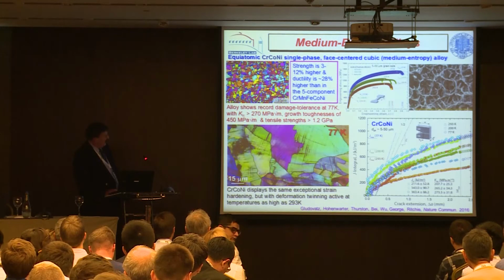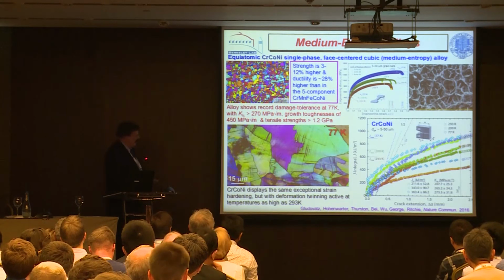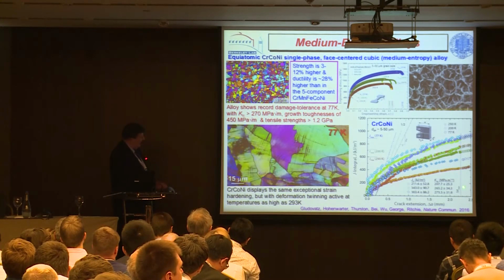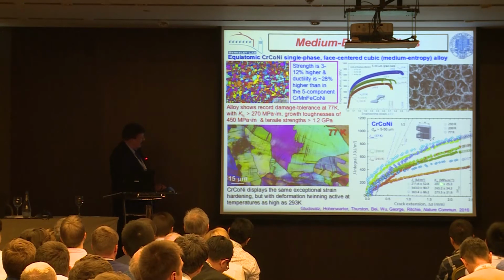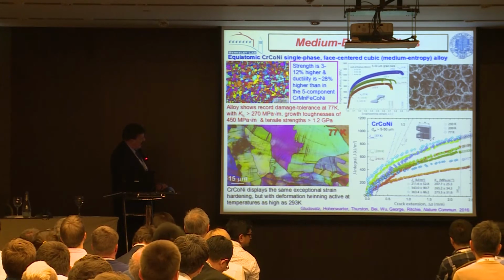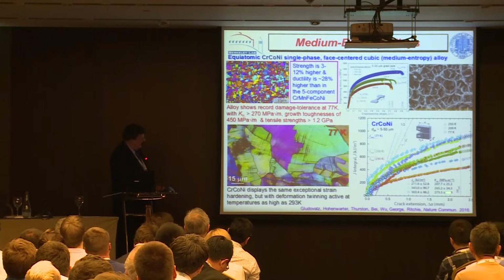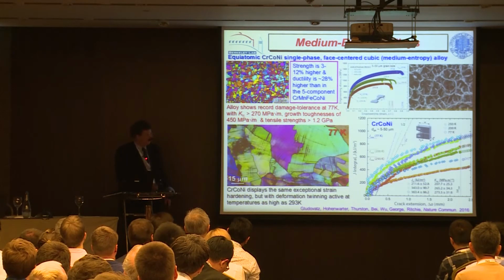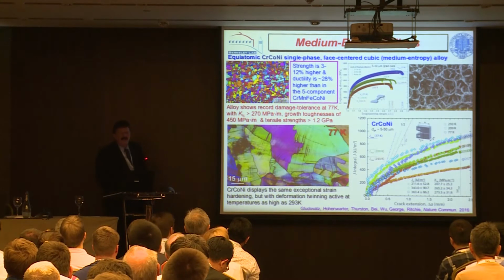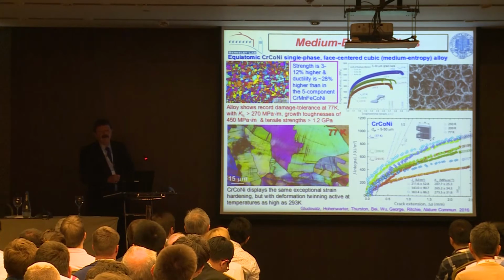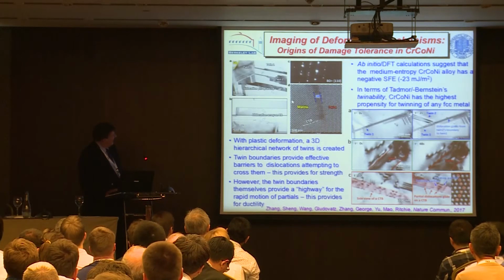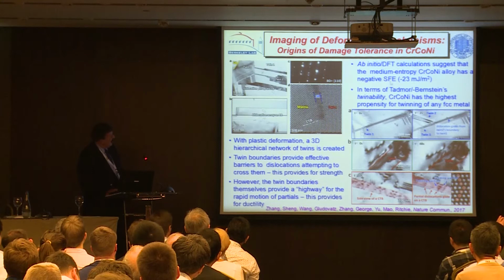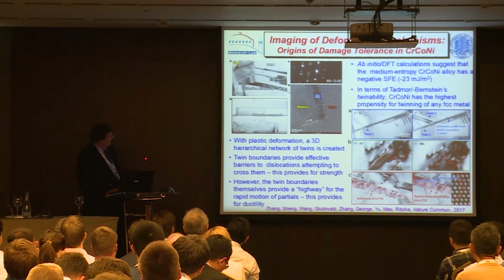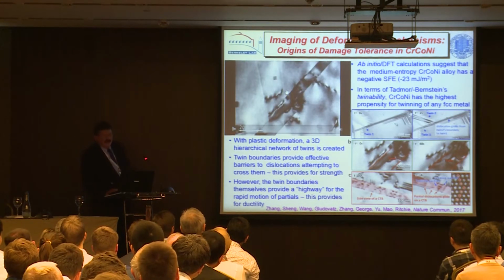When you do the toughness test, the numbers become almost absurd. The initiation toughness is well over 200 megapascals. At liquid nitrogen temperatures, it's 270 megapascals. And the crack growth toughness in valid ASTM is 450 megapascals. These are enormous numbers. And we see it's got very low stacking energy, it has great twinnability, and you see these, again, a duality of mechanisms.